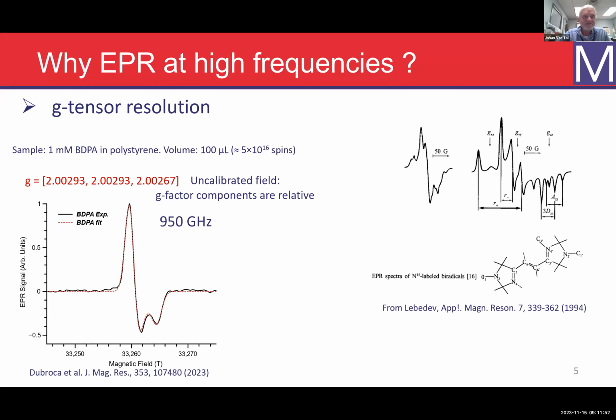So why at high frequencies? One of the reasons is, of course, the G tensor resolution. If you look at the Hamiltonian, the field-dependent term is typically your magnetic field, and that's the Zeeman term. And if you go to extremely high field, this is a recent result at 950 gigahertz in one of our magnets of BDPA, which at typical frequencies up to 200 gigahertz, you get kind of a Gaussian line of 10 Gauss wide. But if you go to these very high frequencies, you can start to see the G anisotropy. These are not quite calibrated well, so there is kind of a shift, perhaps a correction to be made for the isotropic part of this equation, but you can see the anisotropy pretty well.